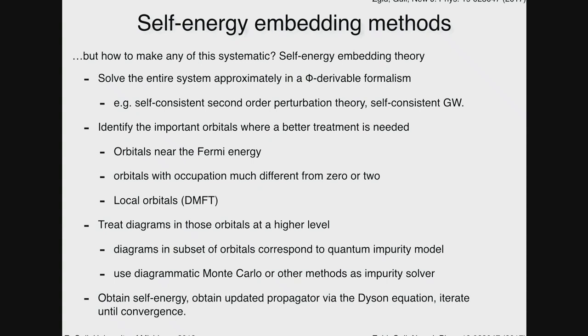But you can take this formalism and you can gradually make it more and more systematic. This leads you to the so-called self-energy embedding theory, where you take the entire system, you solve it approximately in something like a second-order perturbation theory or self-consistent GW calculation. You then don't just take the local orbitals, but you find the orbitals that are most strongly correlated, for example, those near the Fermi energy, those with an occupation much different from 0 or 2, or if you want to do local orbitals, those that are local. And then you treat those diagrams at a higher level.